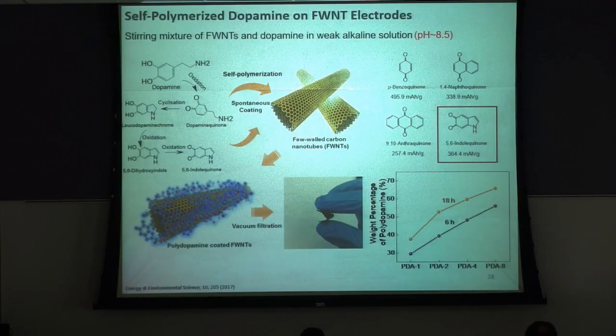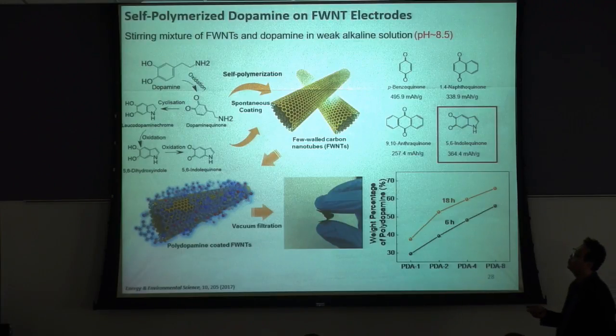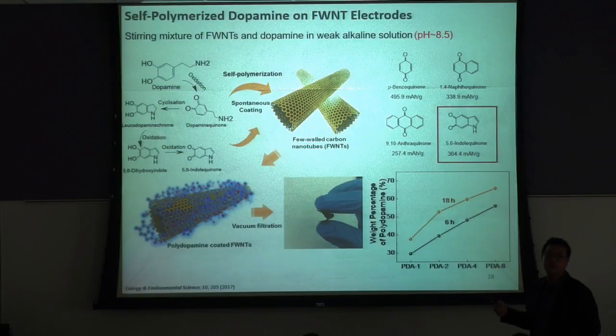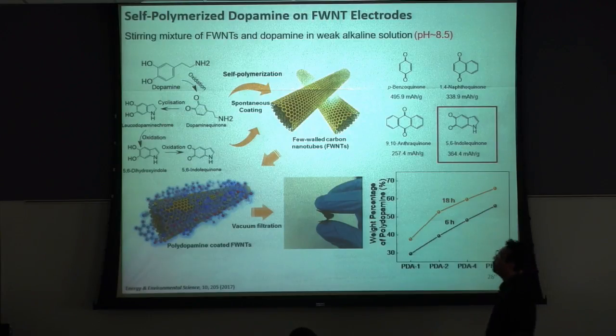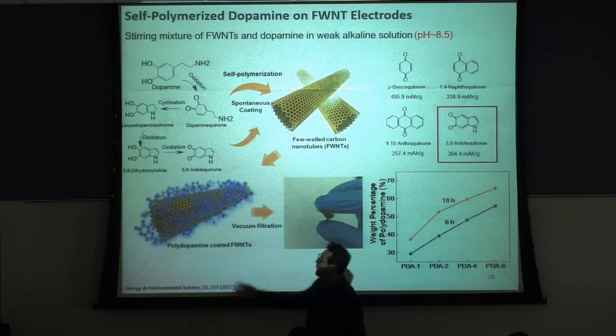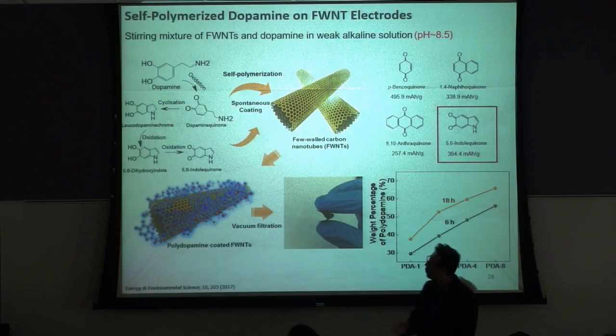Dopamine is an interesting organic material. If we dissolve this dopamine in alkaline solution, dopamine can be oxidized by the dissolved oxygen molecule. They are gradually oxidized, and eventually they are polymerized on top of any kind of substrate. So we simply mix this dopamine with pristine carbon nanotubes, right? Just mixing. Then in alkaline conditions, we are just stirring. Then dopamine can be polymerized on top of these carbon nanotubes, so we can create a very thin polydopamine coating on the carbon nanotubes.